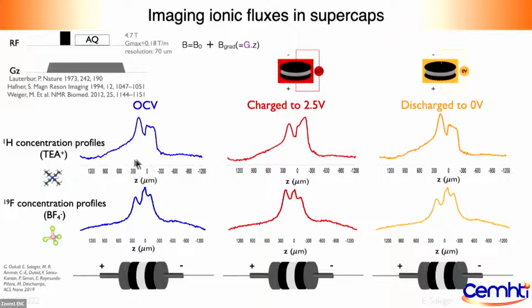And what we can see is that we have profiles, so we can do this for protons to follow the cations, and with fluorine to follow the anions. And at the beginning, when the supercapacitor is assembled and we didn't do anything to it, this is the kind of profile we have. So that's basically the concentration of protons inside this battery. It's distorted by all the interfaces and so on. But as we charge and discharge, we do see changes. And these changes can be followed both for protons and fluorine.